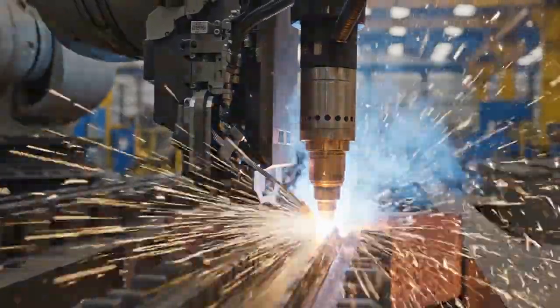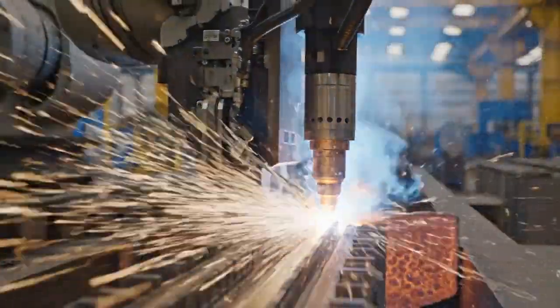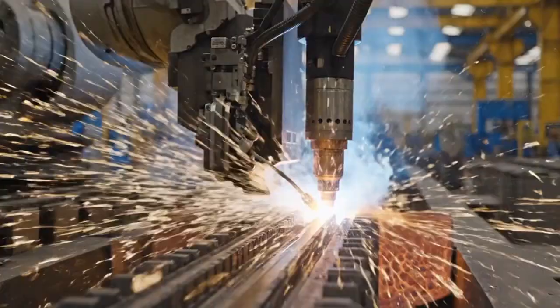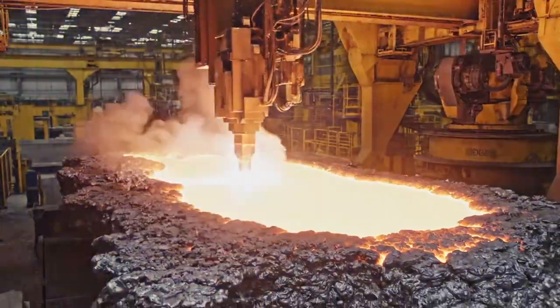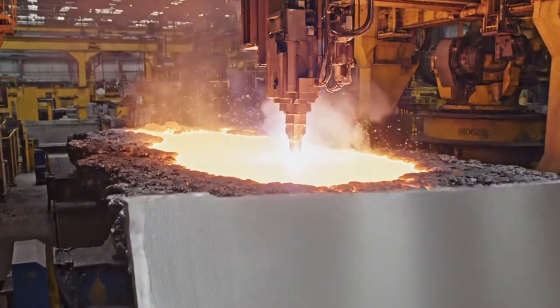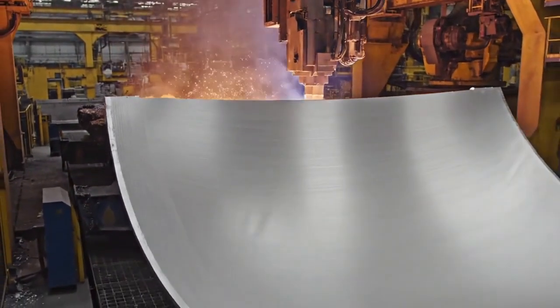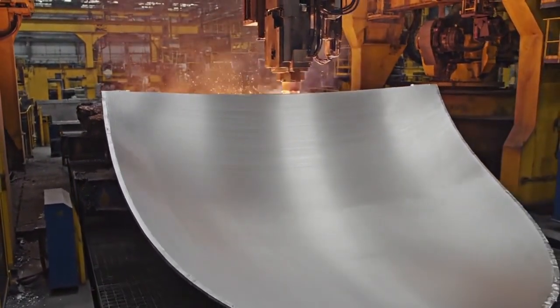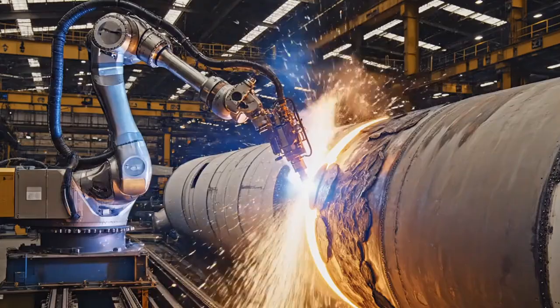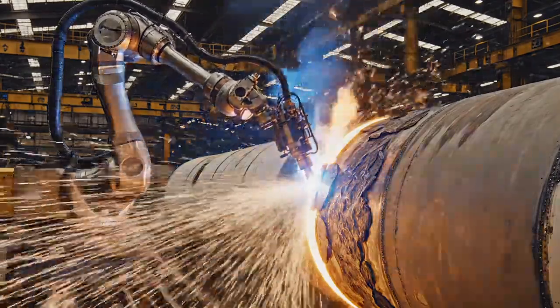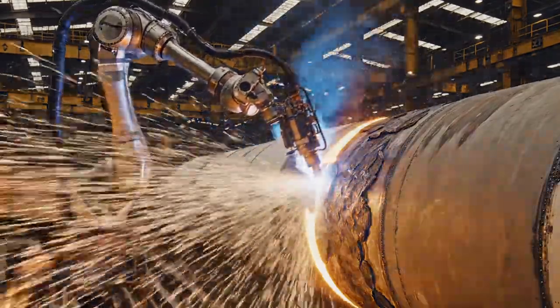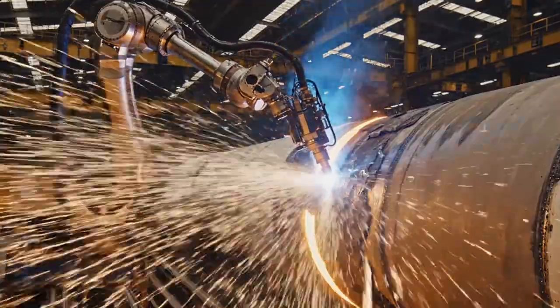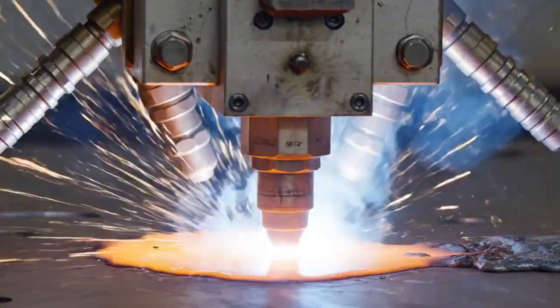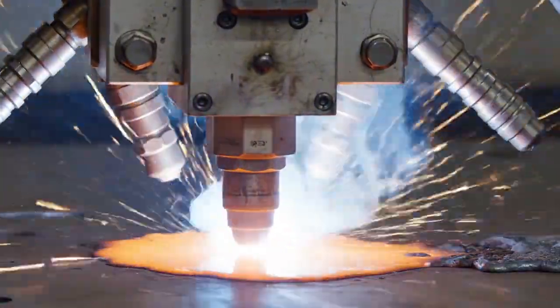When the plasma arc melts the feed wire at temperatures exceeding 3000 degrees Fahrenheit, the molten pool must solidify almost instantaneously to hold its shape, yet maintain a crystalline structure that prevents microscopic fissures as the print head travels at speeds of several inches per second, depositing up to 20 pounds of metal per hour, with a localized shroud of inert shielding gas typically.